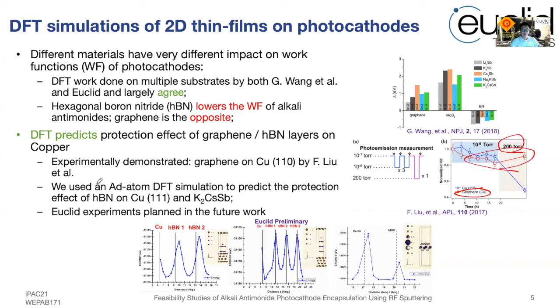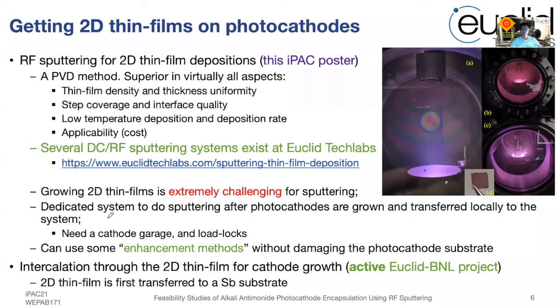We used an ad-atom DFT simulation, basically putting one single oxygen atom above the encapsulated photocathode to show that the total energy for the system increases whenever you go to the barrier of the 2D thin films. This is true for monolayer, bilayer and trilayers of HBN thin films. We did that on copper, and we also did that for K2CsSb, the bialkali antimonide. And we are expecting to do some experimental work in the near future. So the simulations have indicated that this work is worth pursuing.